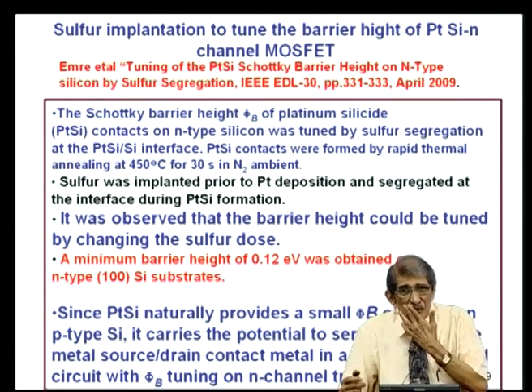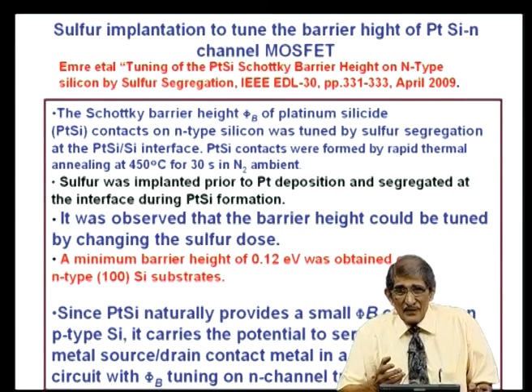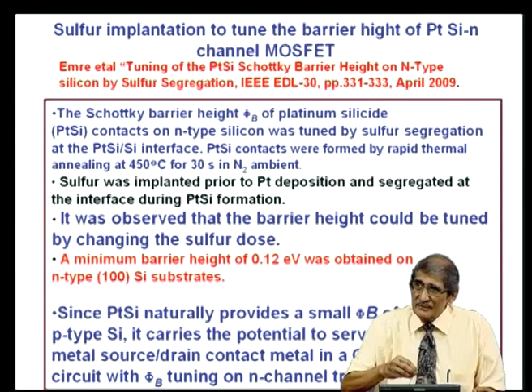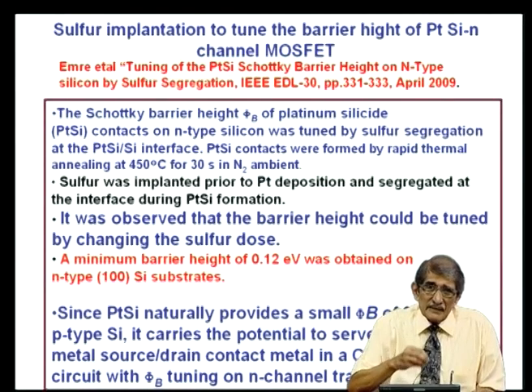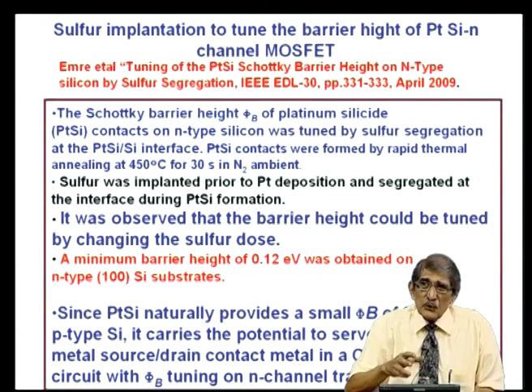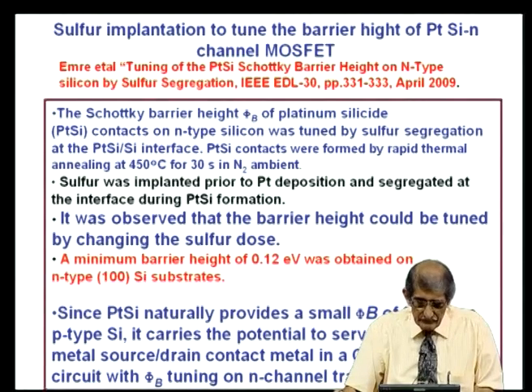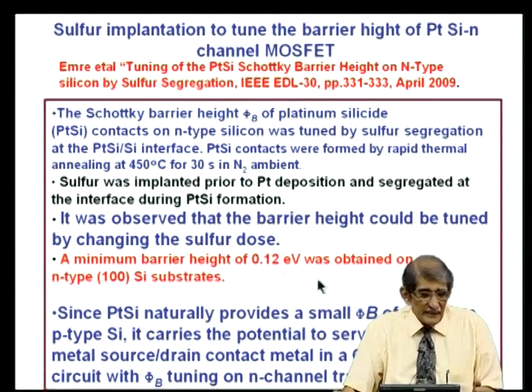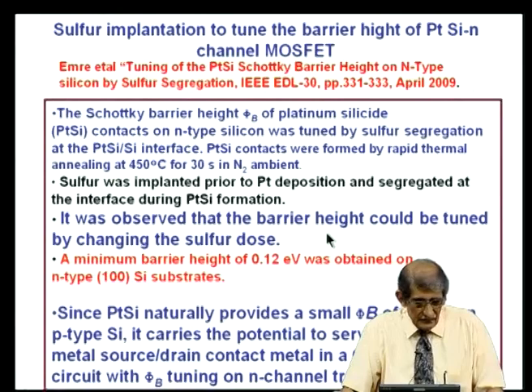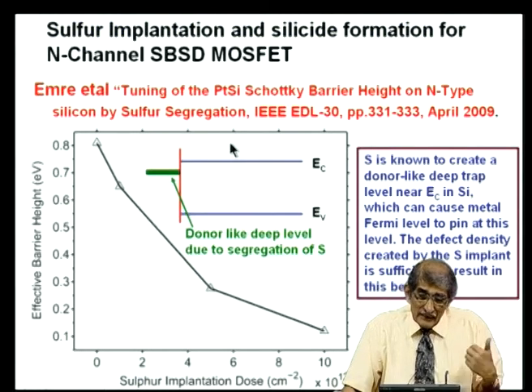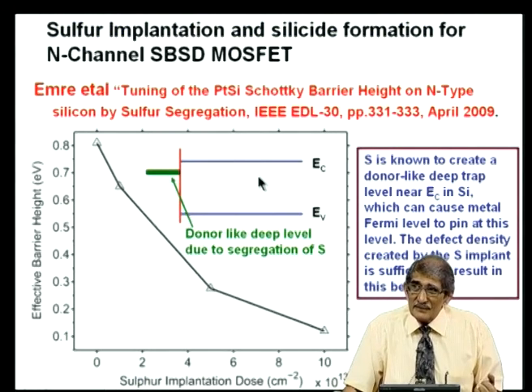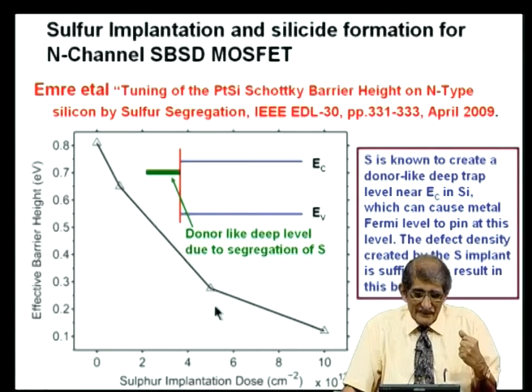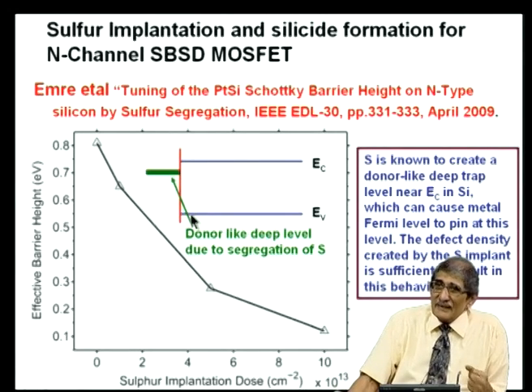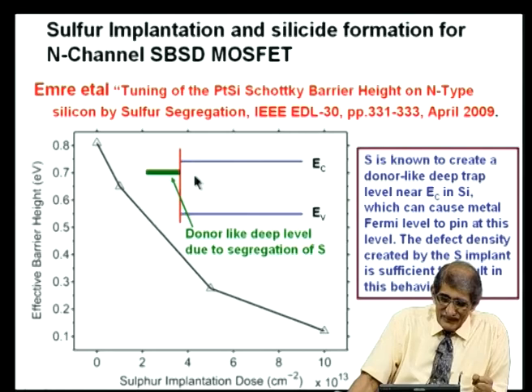In the region where you want to make n-channel devices, you implant sulfur. You can control that barrier height by controlling the dose of sulfur. So, you can make low barrier height for n-channel. So, what happens there? Why this sort of thing? You are changing the location of that pinning.